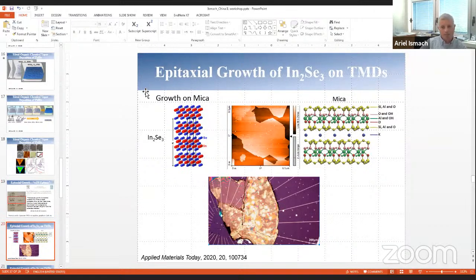We also grow different materials epitaxially. Here you can see an example of a different layered compound, in this case indium selenide, In2Se3, where every layer has 5 atoms, a quintuple layer. Usually this material is grown on mica, and it grows epitaxially. Mica is also a 2D material, a very complex layered compound. But since the mica is so complex, it's very hard to study the growth mechanism and the epitaxial relation. Also, if you want to study the electrical properties and need to transfer these layers from the mica to a target substrate, you sometimes end up with chunks of the mica, because mica is a layered material that can be exfoliated.